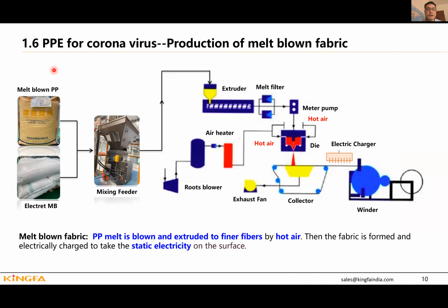Okay, and for the production, this is a whole picture of how we go from the raw material to the melt-blown fabric. First, we need the melt-blown PP and mix it with some electret masterbatch. Then mix it together, and the raw material comes into the extruder. In the extruder, the material is melted and comes to the die. This die has some spinneret plates. In this place, the PP melt is blown by the hot air and extended into very thin fiber, and then comes to the collector.